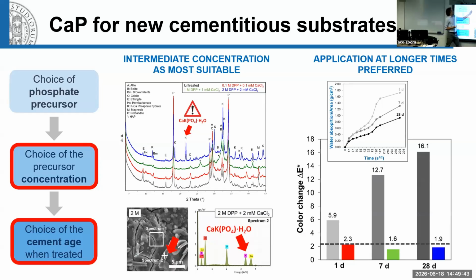What we investigated was what concentration of this phosphate precursor to use in the end. So we compared different concentrations, 0.1 molar, 1 molar, 2 molar, and the intermediate concentration was found to be the best, because otherwise you also form some undesired phases like this one.